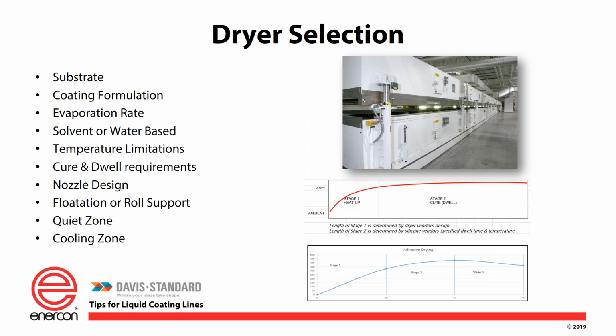Nozzle designs. The nozzle determines what type of air we are going to impart onto the web. You can have a direct impingement where we're blowing hard against the web, or you can have a laminar air which blows along the web. Stainless steel, release coated, they're all different types of nozzles, and for different products and different constructions, we use different ones. Quiet zone, I just mentioned that to you. That's where we have no air on the top, but we're applying a little heat. That allows us to keep a low LEL in the dryer, but yet allows some evaporation to occur so we can start our drying process.